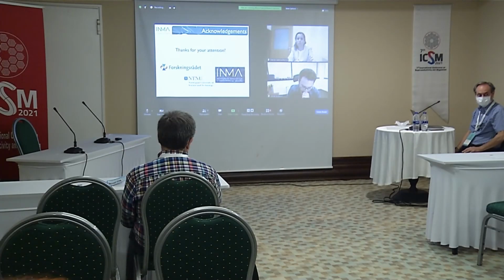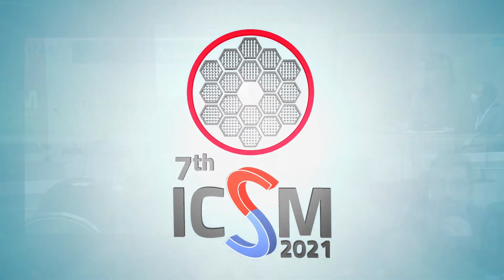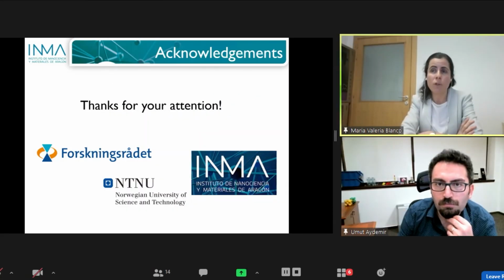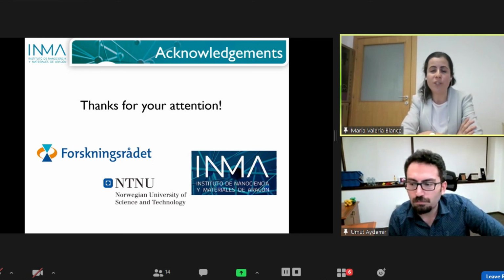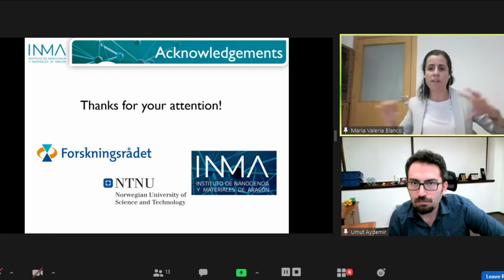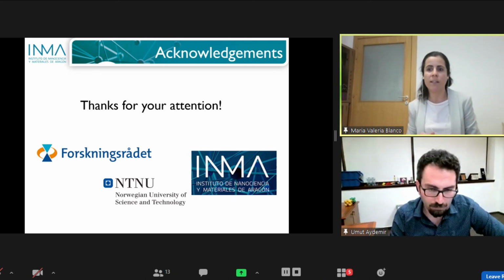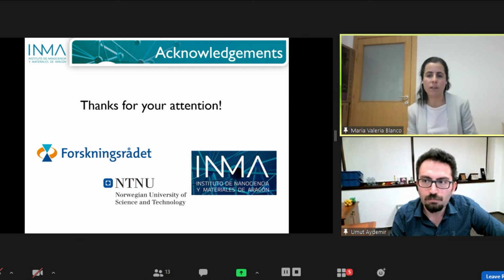You also said that you tried to protect silicon oxide from the electrolyte. I thought it's quite neutral for these kinds of liquids. Well, yes, but it's not. When you have an electrolyte and you are changing the potential, you will have some reduction products of the electrolyte that form what is named the SEI layer, the solid electrolyte interface, and we need to have a lot of control over this interface. It's very important not to have the material in direct contact with the electrolyte, because then it will be more affected by it.